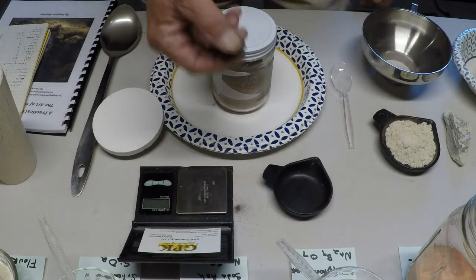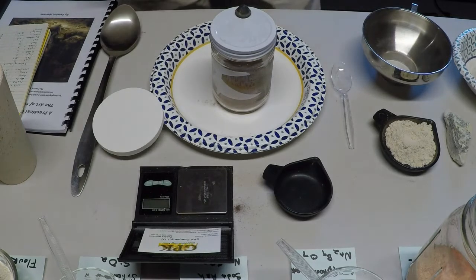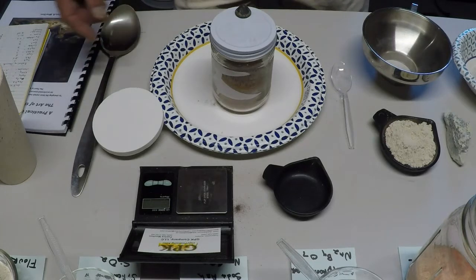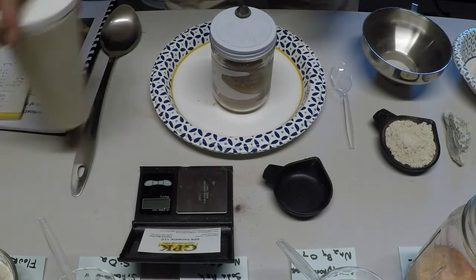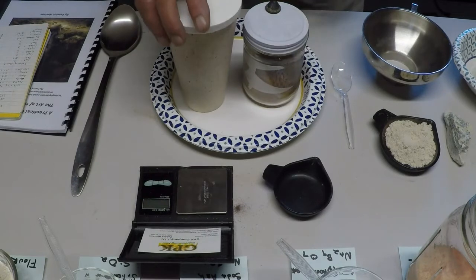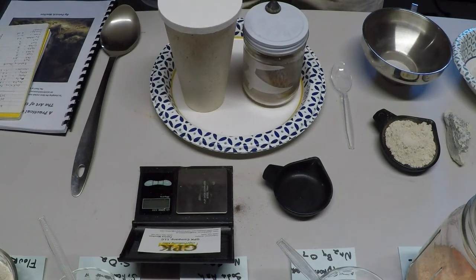So next thing I need to do is I need to set up the KK8. I'll get it set up. We'll pour this into the crucible. We'll put our lid on the crucible. We'll put it in the furnace. We'll run it up to around 1600 degrees until everything settles down for a little bit. Then we'll increase the heat up to about 1950, and we'll hold it there for a while.